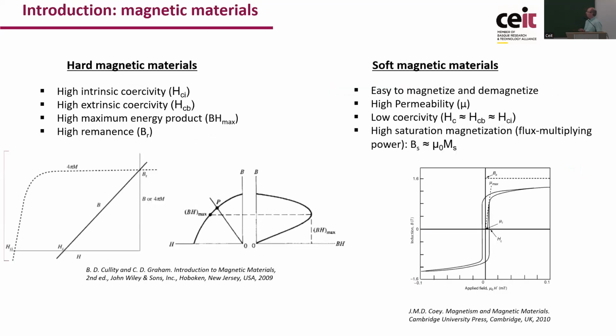First, as I mentioned before, the characteristic of hard magnetic materials is that they have a very broad hysteresis loop. Typically, in operation, what matters is the second quadrant of this hysteresis loop, and in particular, what is called the demagnetization curve. The application and the shape of the magnets define what is called the load line, which is this straight line here, and the intersection of the demagnetization curve with the load line determines the operation point P. The motor or the device and the magnets must be designed so that this point is as close as possible to the point where the magnets are able to deliver the maximum energy, the maximum energy product of the system.